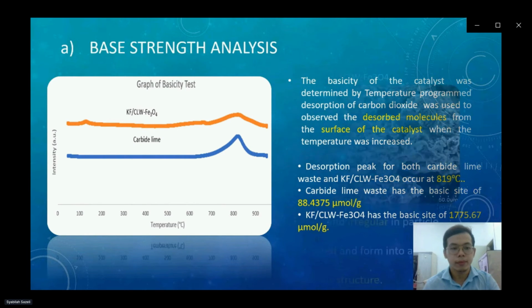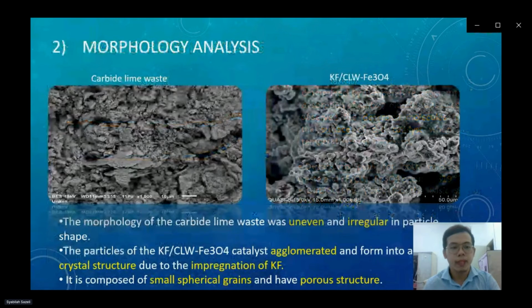Next is the morphology analysis. The morphology of the carbide lime waste, as you can see from the picture, was uneven and irregular in particle shape. While for the KF/CLW/Fe3O4, the catalyst agglomerated and formed a large crystal structure due to the impregnation of the KF. It is also composed of small spherical grains and has a porous structure.